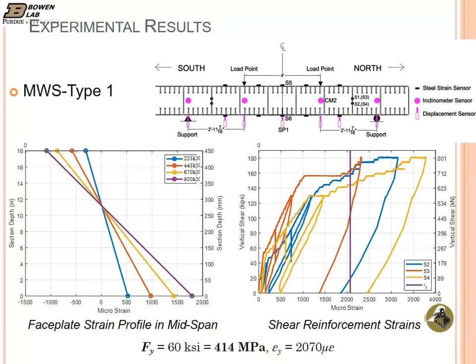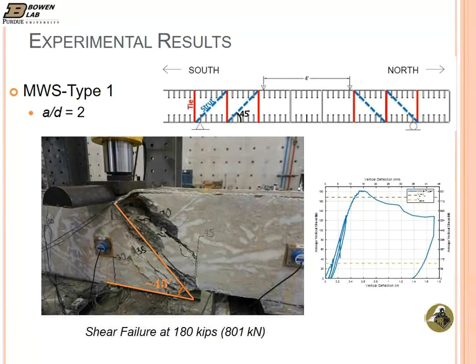But when we looked at web plate strains, there we exceeded the yield strain because we obviously had shear failure, so we forced the web plates and even caused them to yield, as you see in this figure. This is a picture that we took post-failure. You see large concrete crushing in that region, and it's the crack. If you follow the crack, it's almost a 45-degree crack. So you can do a strut and tie truss analogy, as I've shown up there. You have the ties as the web plates, and then compression struts developing in between them. You remember the web plate started yielding, right? And these struts are anchoring to the ties. As the tie starts yielding, it starts to open up. So the strut is becoming weaker and weaker, cracking wider, and it eventually gave up. So that was the experimental behavior for this specimen.